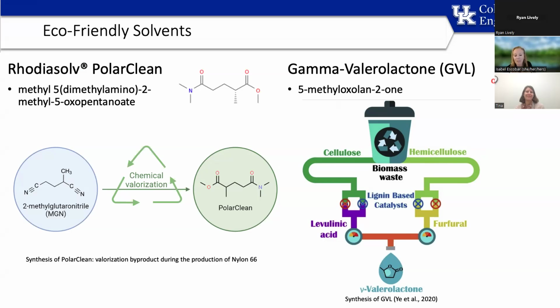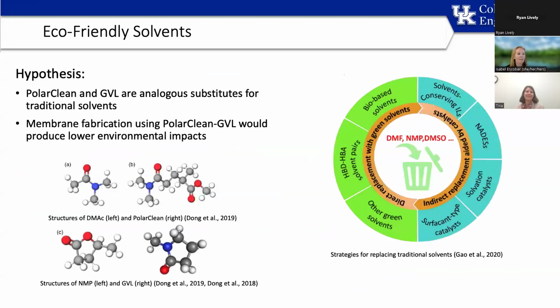It's a byproduct during the production of nylon 6,6. And so the expected sustainability of that is significant. When we started working with this, our thought was that Polar Clean would be the absolute most sustainable one because of the chemical valorization. GVL, on the other hand, is biodegradable, comes from biomass, from cellulose, hemicellulose, and that process. So our hypothesis here was that Polar Clean and GVL would be analogous to traditional solvents in order to make membranes. Now, we published a lot on this.